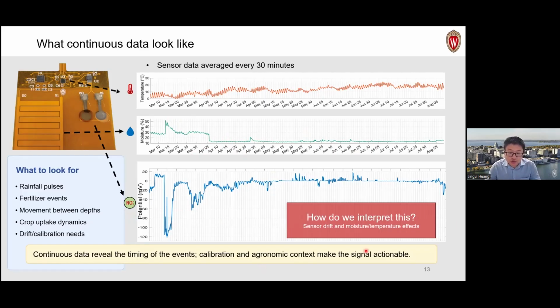The third plot, which is the crucial one, shows the original data of our potential from our working electrodes. As we mentioned before, whenever you see a negative voltage, that means there's an increase of nitrate concentration in the soil. But when you see a more positive voltage, that means nitrate concentration becomes smaller and smaller. But here's the problem. If you only look at the voltage value, it's hard to make a decision because there are many factors that control the voltage. So it's hard to interpret this result.